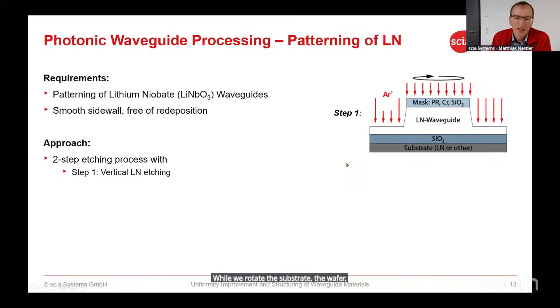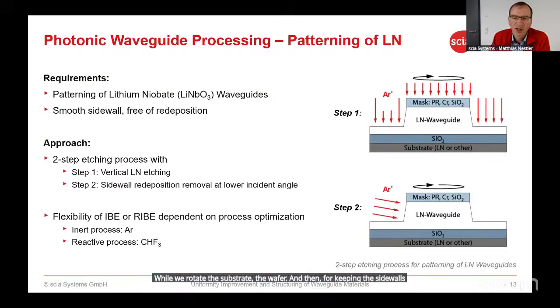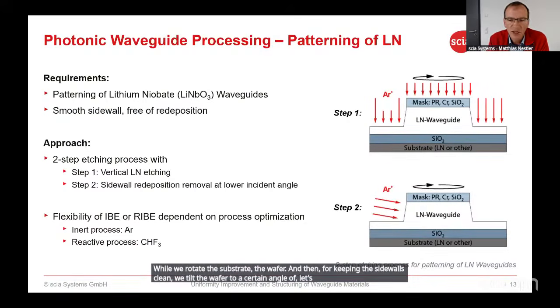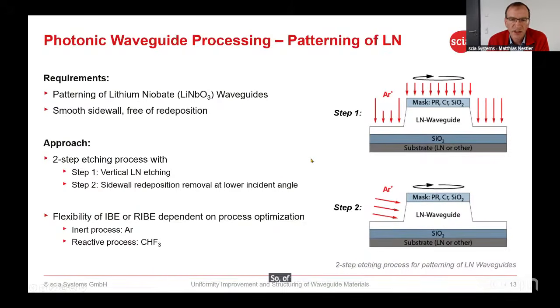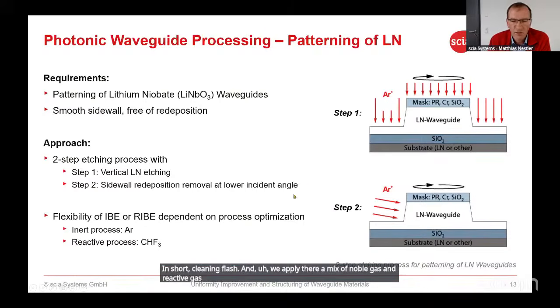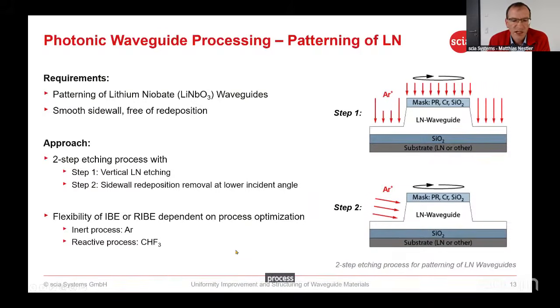And then for keeping the sidewalls clean, we tilt the wafer to a certain angle of, let's say, 70 degrees. And then we hit this side of the structure with an argon beam to clean it up. So, of course, at different times. The first step is a long etching process, while the second one is just a short cleaning flash. And we apply there a mix of noble gas and reactive gas. So we typically apply the reactive ion beam etching process flow with CHF3 as a reactive process gas.